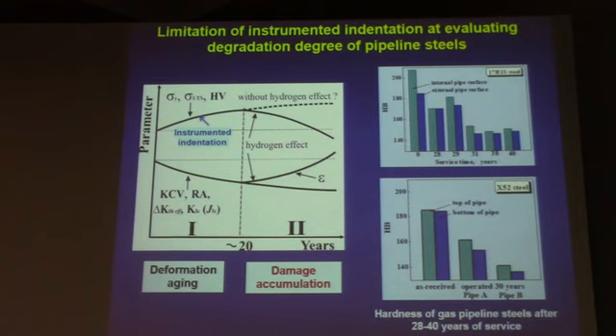So it's very important to evaluate the current technical state of pipeline steel using more non-destructive methods during operation. And the recent trend is quantifying the degradation degree using non-destructive testing methods based on indentation tests. It makes possible to predict first of all strength characteristics of the material, first of all on the stage of deformation aging.